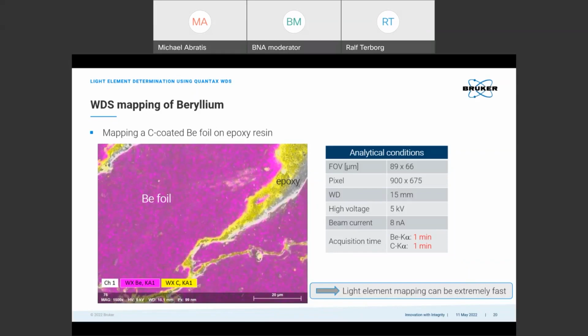Another important factor is the absorption of X-rays that are generated at a certain depth and then move towards the sample surface to reach a detector. Here there is a factor called the absorption factor, and this is defined as the number of X-rays leaving the sample, so those that are not absorbed, divided by the number of generated X-rays. If we have an absorption factor of 1, there is no absorption at all. But normally, especially for light elements, we have quite small absorption factors, and that means that we have significant or massive absorption. I would also like to mention that the absorption factor depends on the path length, and as the takeoff angle and the high voltage, because of the mean depth, change the path lengths, these factors also change the absorption.